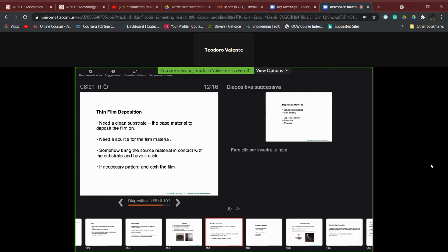In order to establish the fundamentals of these classes of processes, with respect to what is going to happen in comparison with thermal spray technologies, in thin film deposition, due to the fact that the final coated thickness is very small if compared with the thermal spray processes, we need a very clean substrate and as much as possible a flat surface, that means very low roughness values of the materials, which represent the base materials onto which the film will be deposited.